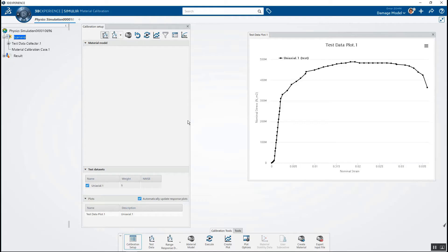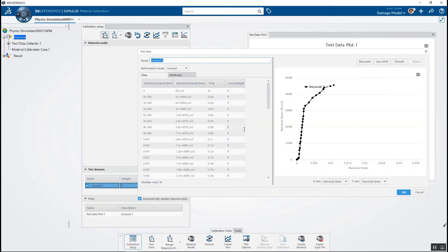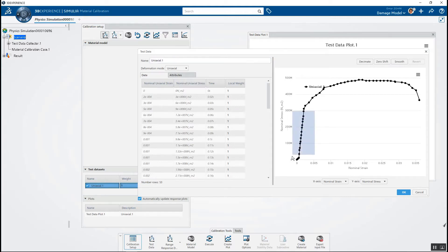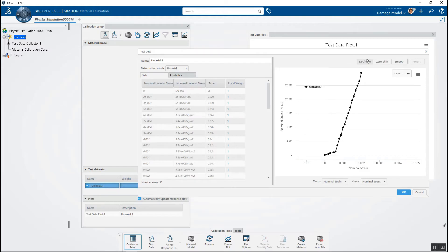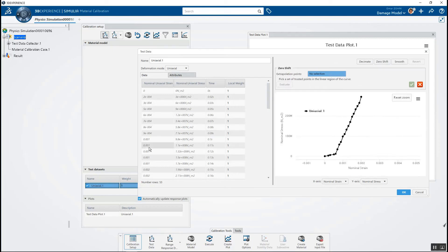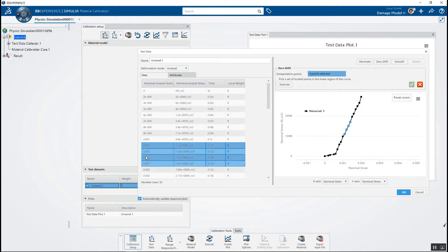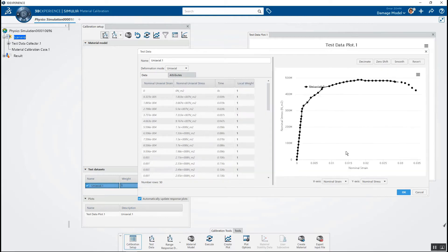I've got my test data selected. The first thing I want to do is a zero shift. I'm going to double-click on my uniaxial data, which puts me in a mode where I can make modifications. I'm going to zoom in on anything under about 300 megapascals and tell the software I want to do a zero shift here. I'll pick the data I want to modify — basically right around where we've got that slack — grab those four points, say evaluate, and there's our new curve zero-shifted to account for the slack.